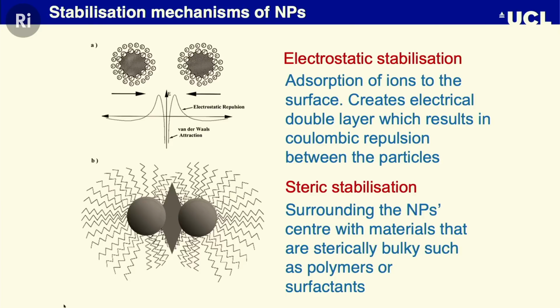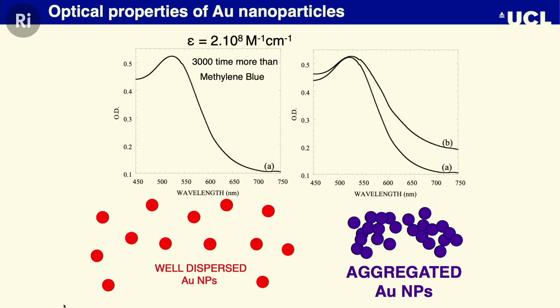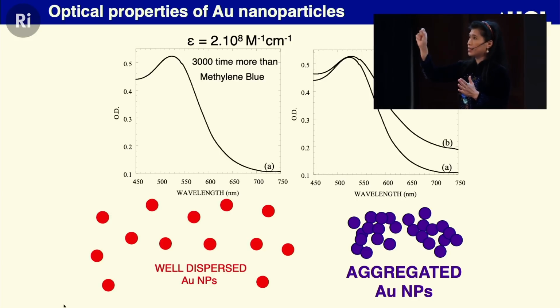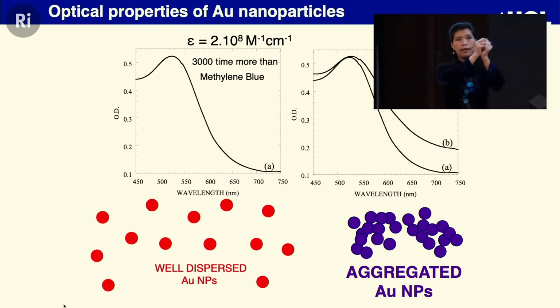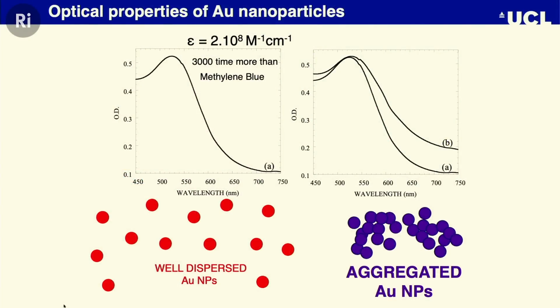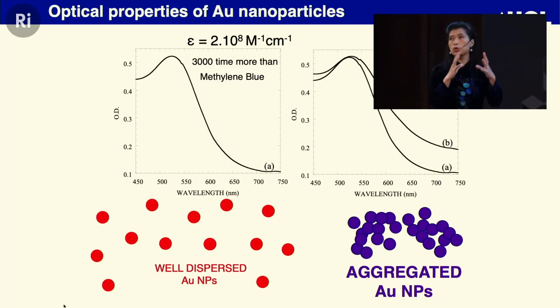So now we exploit the optical property of the nanoparticle when they come together. When gold nanoparticles are very well dispersed, like you can see here, they will have a red color because you can see the peak at 520. So they absorb light at that 520. So that light is missing because it gets absorbed, giving you the red color. When you have some controlled aggregation, bringing the particles together, the electromagnetic wave interacts with the nanoparticles differently when they are clumping together than when they're dispersed. Then they absorb light at a longer wavelength, and you can see that in B they absorb at a longer wavelength. Now the absorption is at a different position, and that's going to give you the color. It turned now from red to blue, okay?